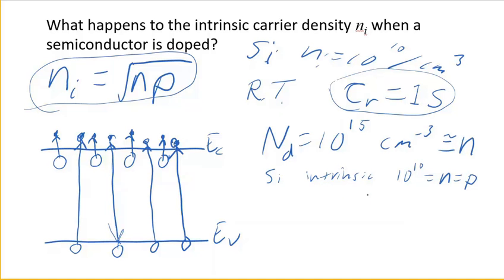you end up with more electrons per cubic centimeter. But that product, n times p, has to always be 10 to the 20th. So if you end up putting 10 to the 15th dopants in there, you're going to have 10 to the 15th n electrons per cubic centimeter, minus a small amount, minus something on the order of 10 to the 10th. Because a bunch of electrons will cancel out the holes.